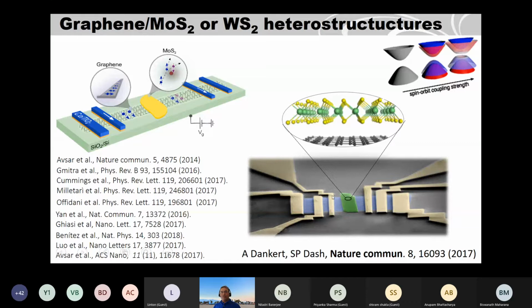So what we do is similar spin transport experiments. As you know, spins are very sensitive to spin orbit coupling. So we inject spins from this electrode, and the spins diffuse in this heterostructure, which is graphene with MoS2, and we want to detect the spin at the other side. While spins are coming into this heterostructure area, we can find out how they interact.